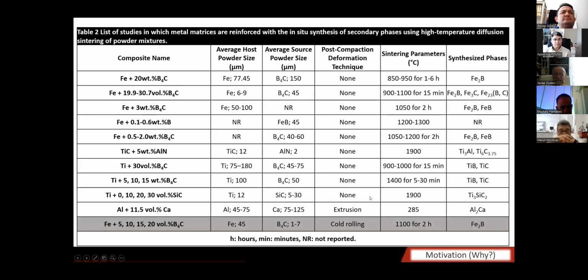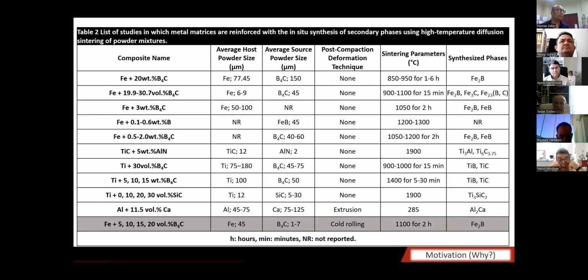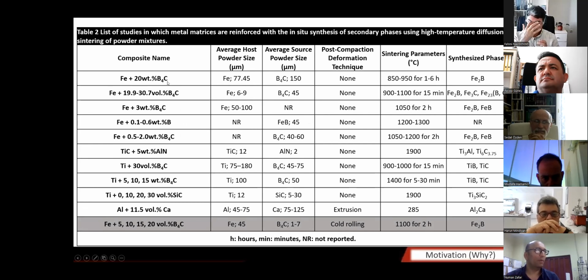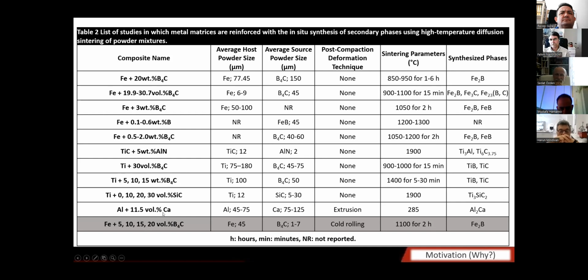Here is another paper. This is an unpublished table from my thesis in which I have shown that the studies are very rare, but I have been able to find maybe 10 or 12 of them, in which iron has been reinforced by B4C particles, and titanium has been reinforced by B4C particles. Aluminum has been reinforced by calcium. These studies used powder metallurgy, as I told you, and elevated temperature treatments to in situ synthesize these ceramic phases inside the material. But none of them have used post-compaction techniques after compacting the powder forms, except aluminum, in which they used extrusion, but they have not produced bulk materials. This study belongs to composite wires.